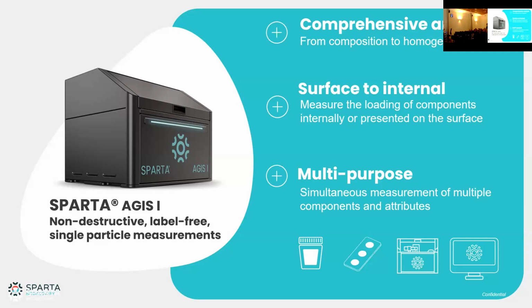And in terms of the sample, is there some requirement regarding the concentration of the particles, for instance, or if there are some components that emit light and can interact with a laser, what are in general the requirements? Yeah, absolutely. The main size that basically always works is about 40 to 400 nanometers. For some denser particles, we can go a bit smaller. If you go higher than that, you just need to make sure that they're still Brownian in motion, still floating, and that they don't all start to sink to the bottom. That's where the higher cutoff comes from.